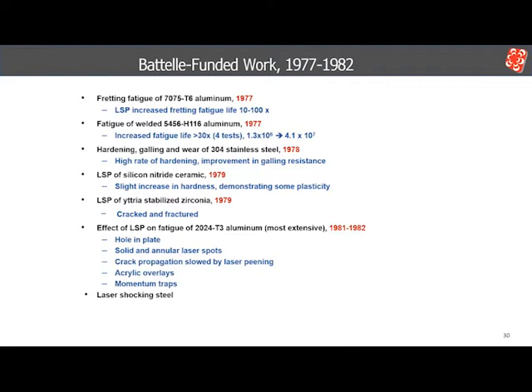We also had the idea to take advantage of the volume increasing tetragonal to monoclinic phase change in tension in yttria stabilized zirconia, to use the tensile shock wave reflecting from the back surface to drive transformation to the higher volume phase. This would then create a compressive residual stress in the back surface and add additional toughening to this ceramic. It didn't work. Battelle also funded an extensive investigation of fatigue of 2024 T3 aluminum and the effects of